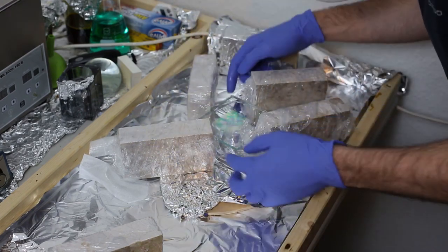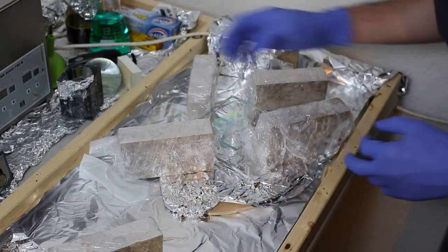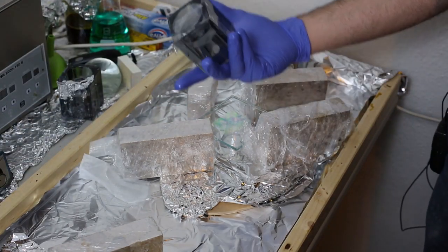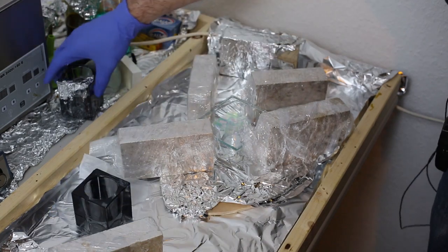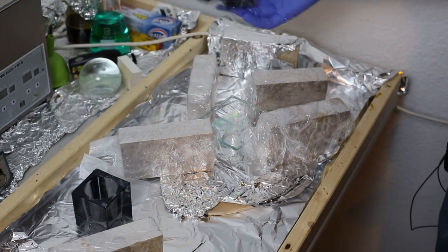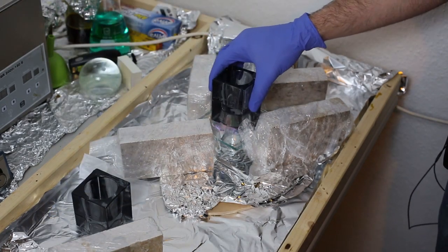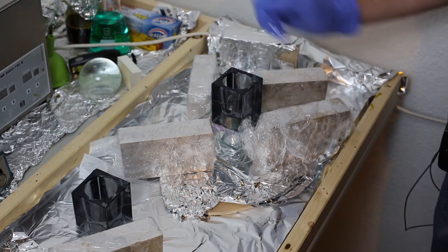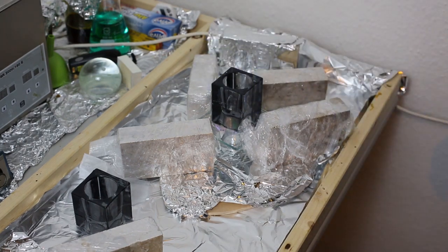In a final step, I put a weight on top of the hologram. The weight is removed after 1 hour. It's just there to apply some initial pressure on the glued glass plates. If the weight is left on there for too long, there will be visible force lines in the final hologram.